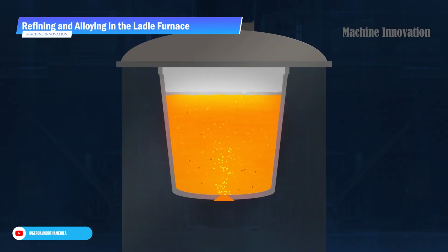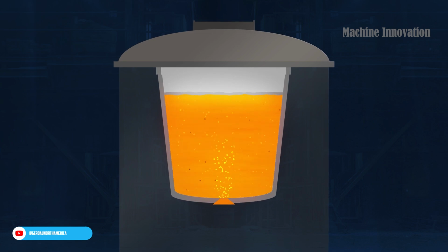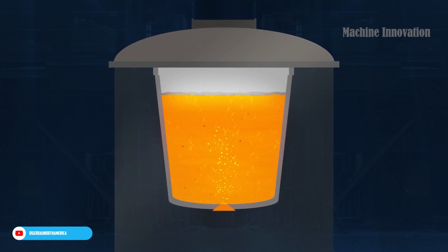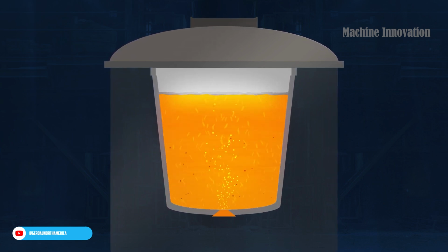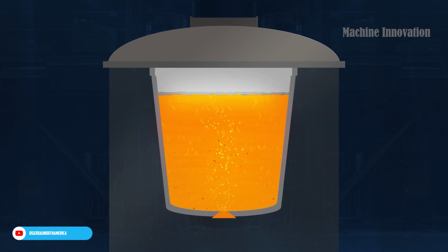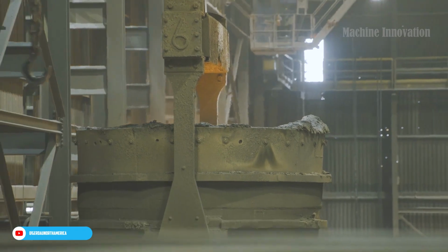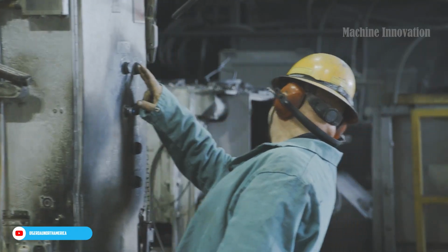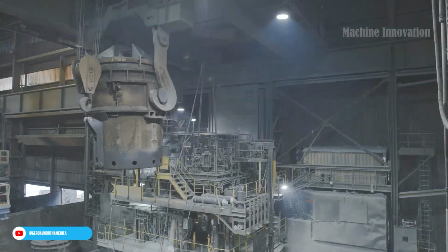At this stage, Gerdau covers the steel with a synthetic slag, which serves two purposes. It insulates the steel to prevent heat loss, and it prevents the molten metal from oxidizing by blocking exposure to air. This controlled environment is essential to avoid impurities and to keep the metal's quality intact.